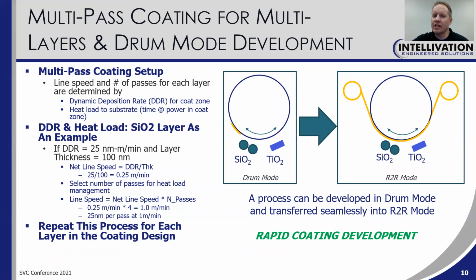The other thing on this slide is talking about roll-to-roll mode and drum mode. Another thing we're able to do is run through all of this characterization in a drum mode, where we attach substrates directly to the drum. In that case, we can attach things like glass microscope slides or silicon wafers, where we can get better characterization than perhaps on a plastic substrate. This is a technique that we find really useful and really accelerates development of coatings.